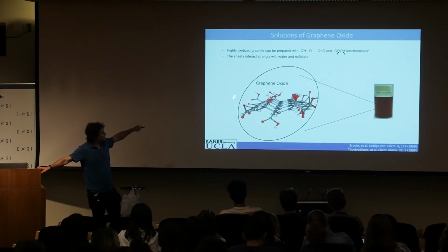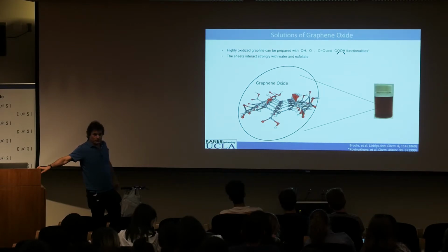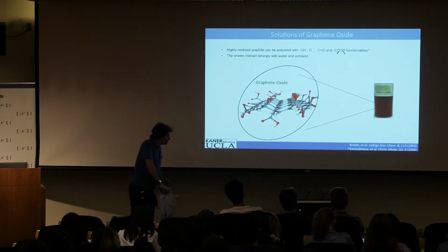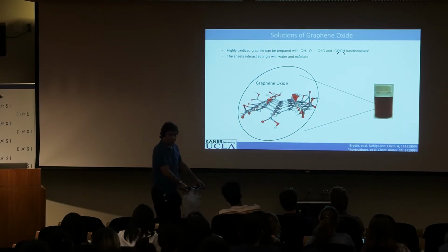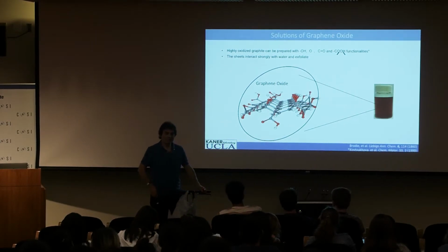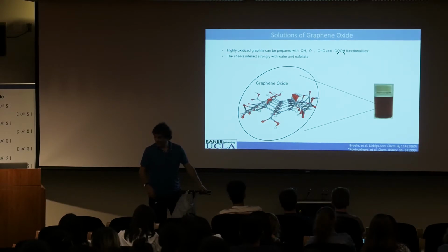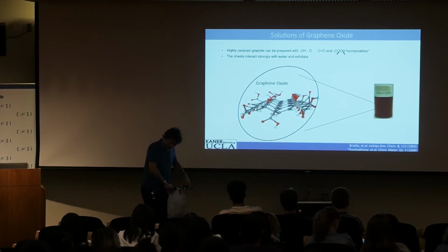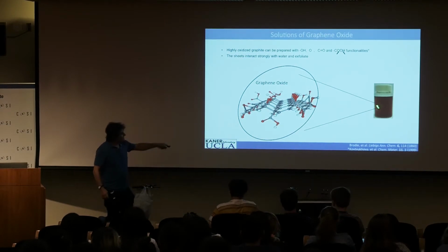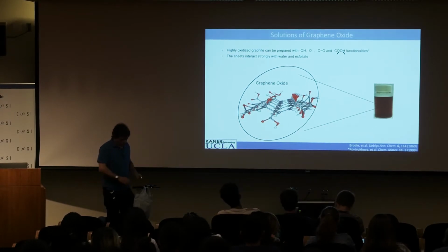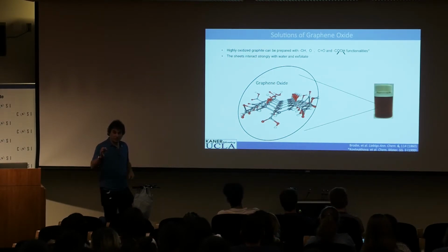And it turns out that there's a material called graphite oxide. It's really graphene where it's all oxidized. There's carboxylic acid, there's hydroxyl groups, there's epoxide rings. And the neat thing is once you oxidize the edges, it disperses in water. And this has been known for a long time. Here's a paper from 1860. Would anybody guess that chemistry goes back over 150 years? Kind of surprising, right? But scientific papers were written back in the 1800s. So in the 1800s, they knew you could oxidize graphite and put it in water. What they didn't know till the last 10 years is this material is in water as single sheets.